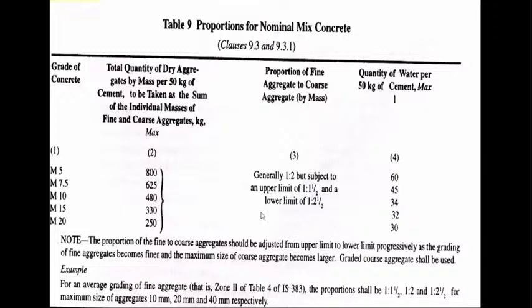The final column gives you the quantity of water per 50 kg of cement, which is the maximum quantity of water. So for example, in M20, the maximum quantity of water which you can use is 30 kg per 50 kg of cement, provided your aggregates are absolutely dry. If you already have some moisture content, then you cannot use this 30 kg of water. You will have to reduce it to the extent of whatever moisture is already present in your aggregates. For example, if your aggregates already have 5 kg of moisture, then you cannot use 30 kg, you should use only 25 kg.